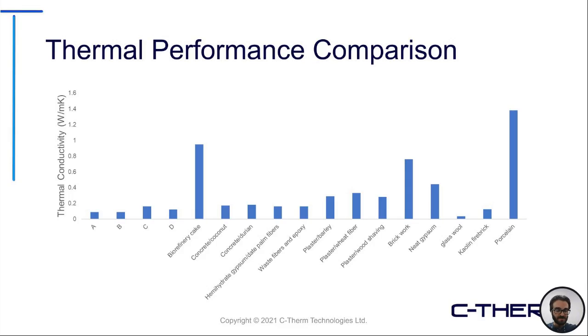So for samples A, B, C, and D on the far left, we can see, generally speaking, very low thermal conductivity response. Sample B did result in the lowest overall measurement. Therefore, that was the sample combination that was best suited for their study. But then they also compared it to some other traditional materials and also other bio-based additive samples. So, as an example, concrete coconut mixtures, different plaster, wheat fibers, natural wood shavings. A lot of these additives that we're seeing in this list here are things that are either waste products or simply discarded through the process of their build.